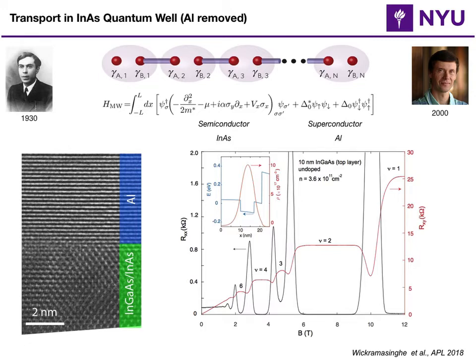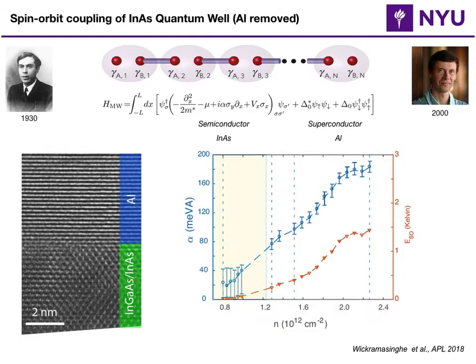The density, you can tune it by doping, and the whole band engineering becomes very important, because you also want to get a good overlap with the aluminum. You really don't want your structure to be buried, so there is no interaction with the aluminum. So that checks out as a good 2DEG.